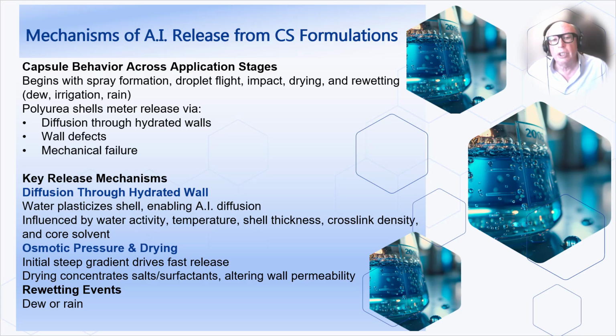Drying concentrates salts and surfactants, altering wall permeability and causing mechanical shell failure. Then rewetting events, dew, irrigation, rain, each causing wall swelling and rupture, potentially triggering more release. Add chemical degradation from hydrolysis and photolysis to complete the picture.